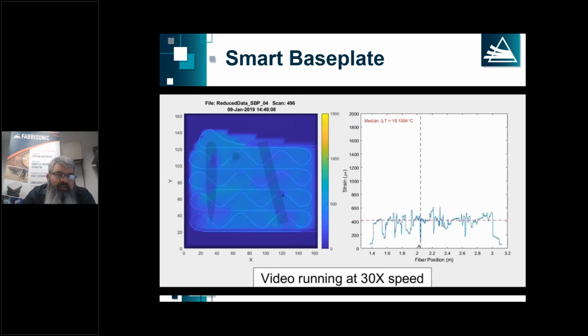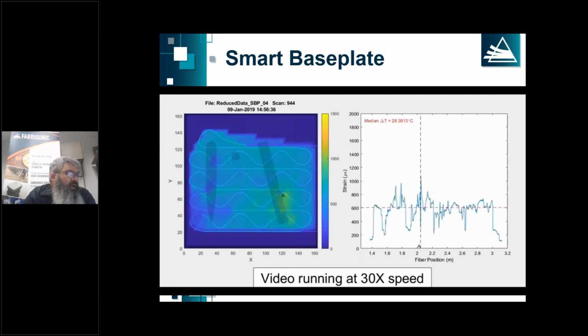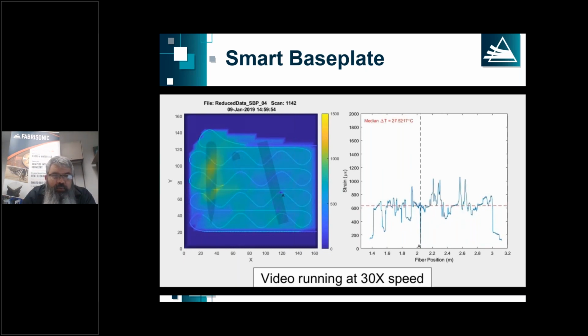And the white line that you see is the path that our fiber optic cable took. And you can see that's kind of like a strain rosette. So what we're trying to achieve is the ability to get both strain magnitude and direction, so the vector of the strain loading in this base plate while the powder bed build was evolving. We put a whole bunch of other sensors into build plates, but this is a strain-based build plate. You can see the strain evolve over time.